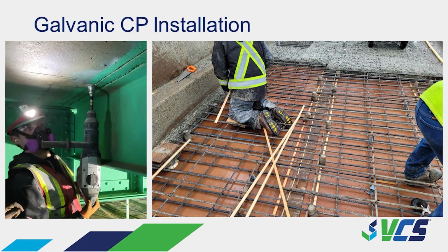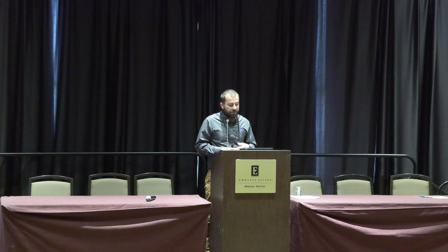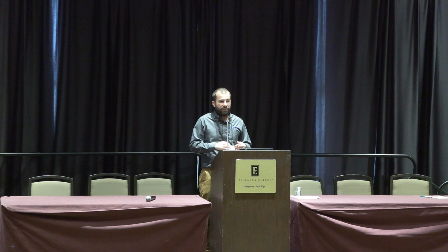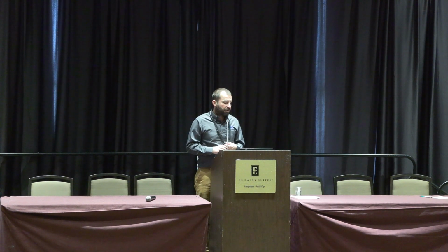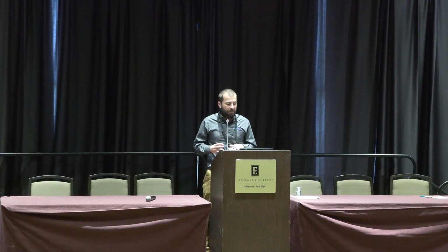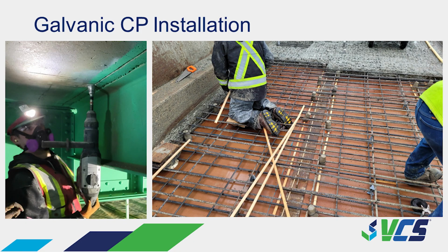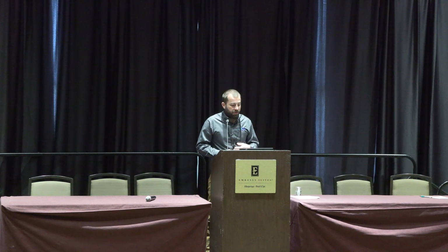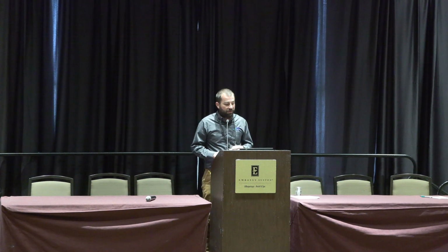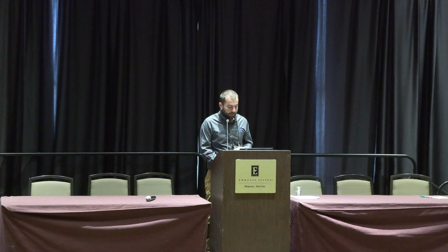The galvanic system, again, is going to be a localized application. You can see there on the right where they have some full depth repairs. They can just put the anodes right into those repairs, connect them to the steel, and they're done. They're not wiring that to anything beyond that. They're just connecting those in the areas where they have corrosion of the top of the steel beam, protecting that and stopping that corrosion in the area. In areas where they're not doing full repairs, they're drilling a hole from the underside and grouting those anodes in from the underside. Again, these anodes are going in only at those targeted areas, so it's very localized and targeted. They're not coring along every single beam. They're just doing it in the areas necessary.